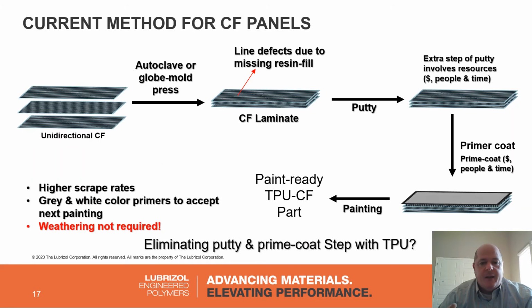The process is very similar to using the exposed weave. The key difference here is that with unidirectional, when the part dries, you get little dry lines inside of it. You can see the little red dot up in the middle upper animation there, where you can actually see some of those dry lines. So when you get those dry lines in the particular part, you typically have to have a human inspection where they're looking for the dry lines, reputtying, doing a primer coat, going through the process one, two, three times to get a smooth surface so that they're able to then paint the part and have it ready for use.